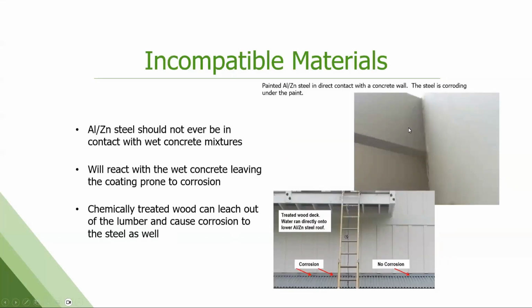Concrete, wet concrete up against these painted panels. You got to have a water barrier or you get moisture into that steel substrate, causes corrosion. Treated wood is a big one. So treated wood, either wet wood that's still damp or wood that's been treated with fire retardants that contain copper, are problematic with painted metal. You will get corrosion. So this deck right here had treated wood. The water was running directly off of it onto the metal panels below, causing areas of corrosion. As soon as you got out past the deck where you didn't have that water runoff, the panels were fine.